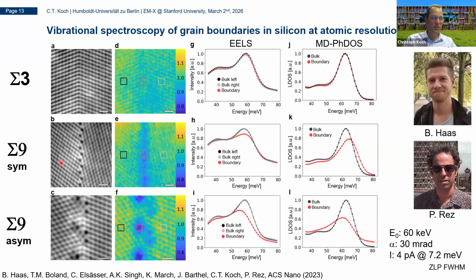But going to the sigma 9 grain boundary, you can see there are these pockets with 7-membered rings. And actually the phonon spectrum, if you focus on the 60 milli-eV peak, does change quite a bit. And if you go to the asymmetric grain boundary, you can see the structure is even less symmetric, and you can see even bigger pockets of different structure, and the deviations are even stronger. And you can see the deviations are mostly affecting the 60 milli-eV peak, not so much the 40 milli-eV peak.